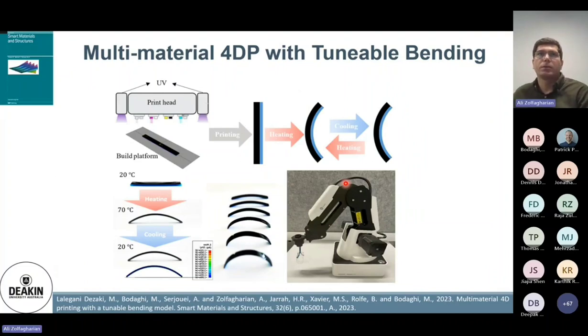In our other recent work, we developed this two-layer, or multi-material, 4D printing with tunable bending, where we use again a shape memory polymer, and also a TPU-like material such as Vero and Tango, or Agilus, which was recently introduced instead of Tango as an elastomer. We printed two different layers with different thicknesses, and then we could achieve different bending angles based on the height of the layer, and also by changing the printing parameters, as a gripper.